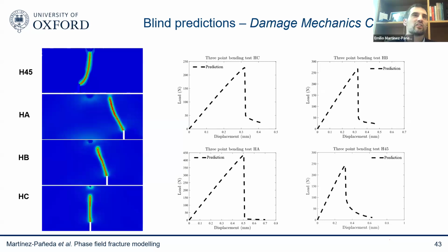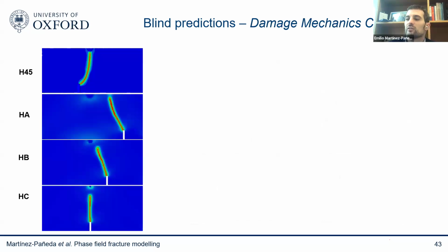So we did that. We said, okay, they give us the geometry of their experiment. So we went with our model and we said, okay, we predict, you can see here they have different 3-point bending configurations, where they have notches in different locations. So you get kind of mixed mode cracking. And then we didn't know what the experiments look like, but we ran our simulations. We predict these crack trajectories on the left, and we predict these force displacement curves. We send it over to them, and then when they have the results from everyone, they release the data. And this is how the data look.